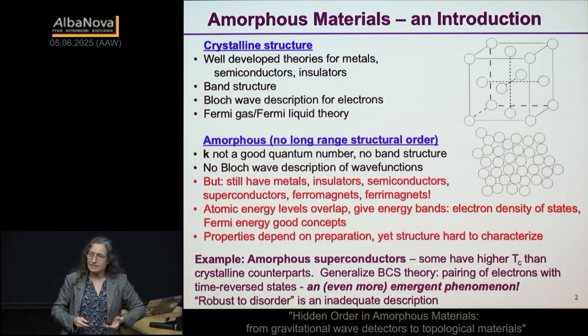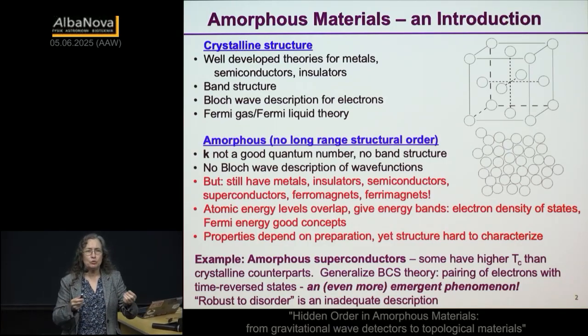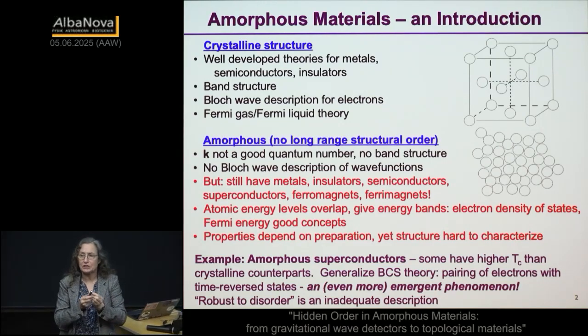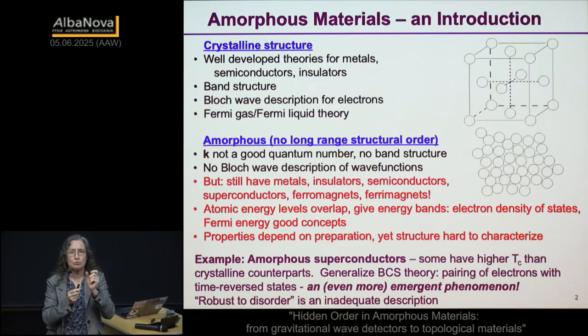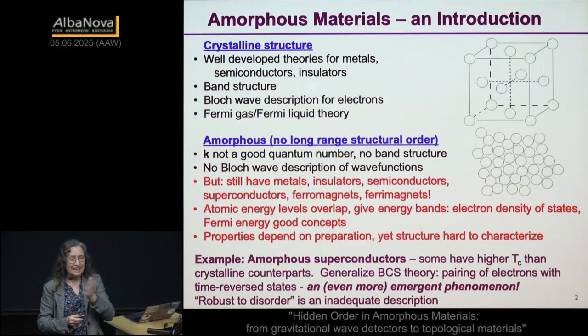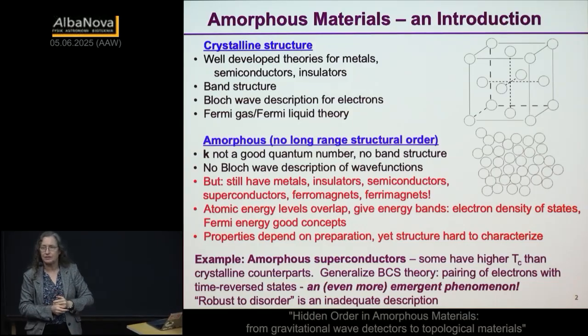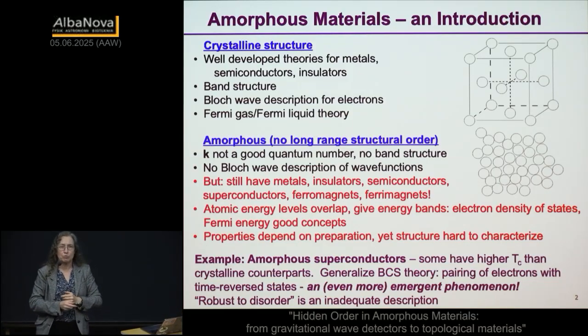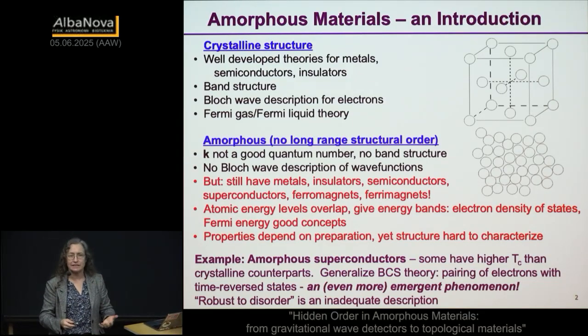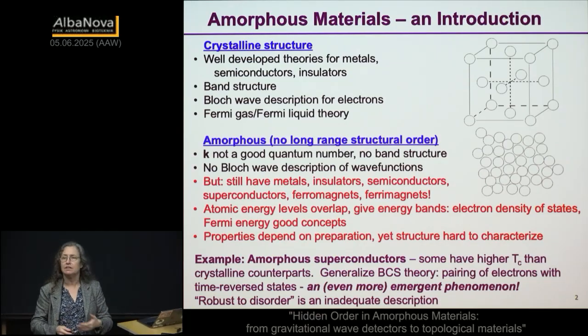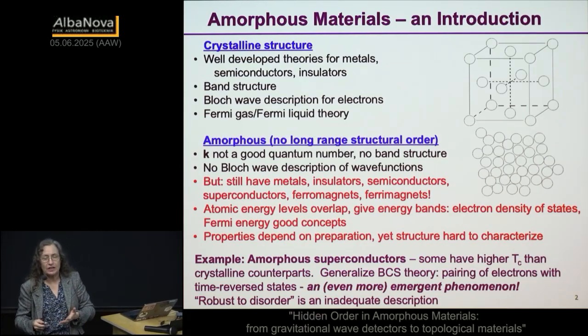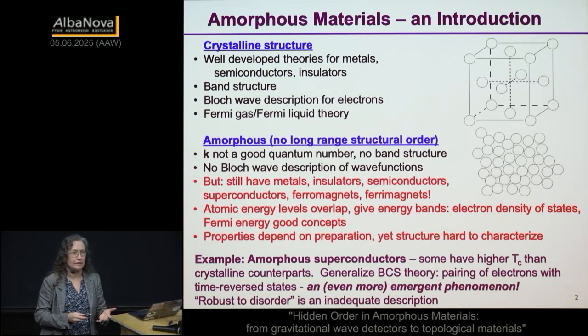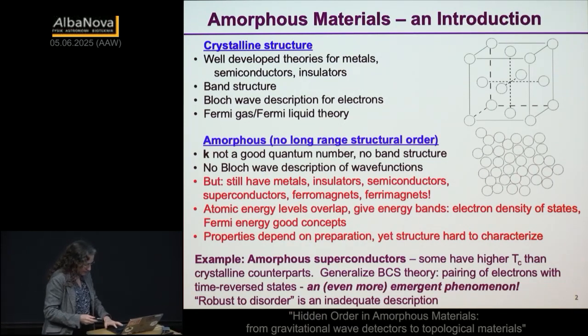I'd say the other thing that's interesting about this is when I make the Cooper pair that small, which I do because there's so much scattering, the Cooper pair is now very, very small. That's actually pretty good for superconductivity in a lot of ways. It makes it more type 2. It tends to enhance the upper critical field. So it's actually kind of a good thing to make it disordered in this way. All right, so that's just a philosophical point.